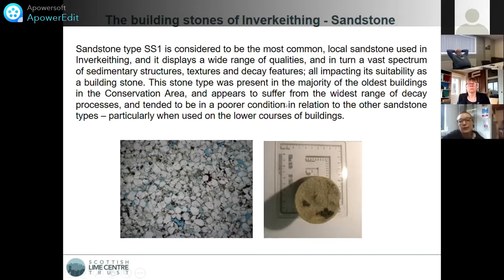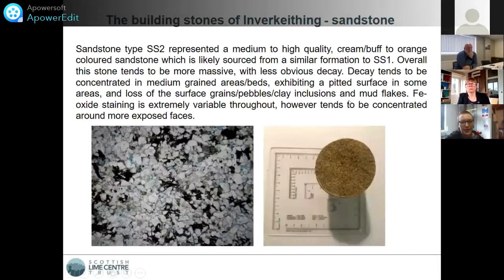And as I said, we did see that this stone had the widest range of decay processes and tended to be in poorer condition, particularly when used on the lower courses of buildings. And that'll have a lot to do with moisture and de-icing salts, as I said.